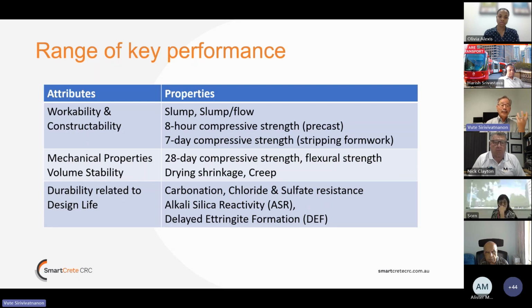And apart from the normal exposure, either a carbonation-induced corrosion issue, chloride-induced corrosion issue, or sulfate, don't forget about the possible deterioration mechanism due to alkali-silica reactivity, and also the possibility of delayed ettringite formation, which may affect concrete that may be cured at very high temperature.